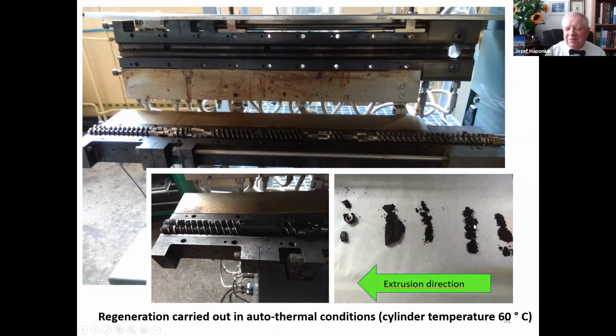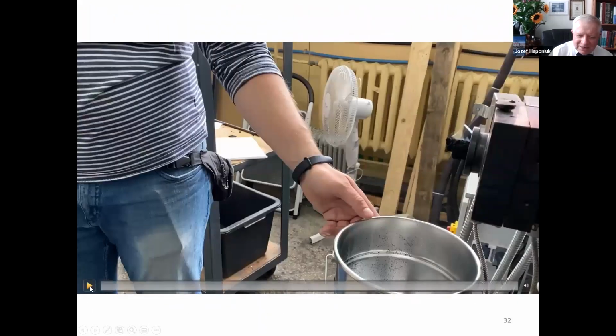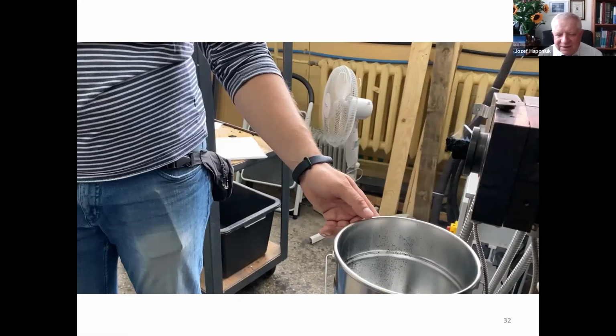different stages of reclamation. So at the beginning we have a powder, and after that when the crosslinks are broken, we have a product which could be formed using some stress pressure. So it's already a moldable product. So we can try to see a short film. So you will observe the reclaimed rubber coming out of this double screw extruder, and after that the calendering of it, showing us that the reclamation was really done to this material.